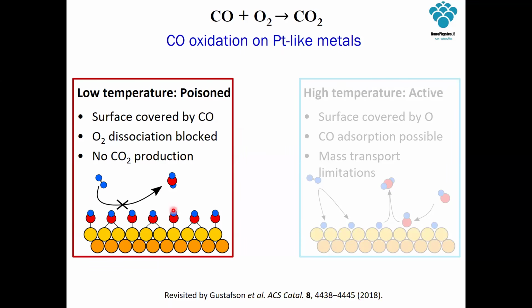So these transition metal materials, they're very prone to get CO stuck to them. So you see it here. This is platinum, or this could be rhodium, and CO sticks, in an environment like we have here, to the surface, and then it occupies all surface positions. And then, of course, oxygen cannot dissociate anymore here. Everything is full. So we have no CO2 production.